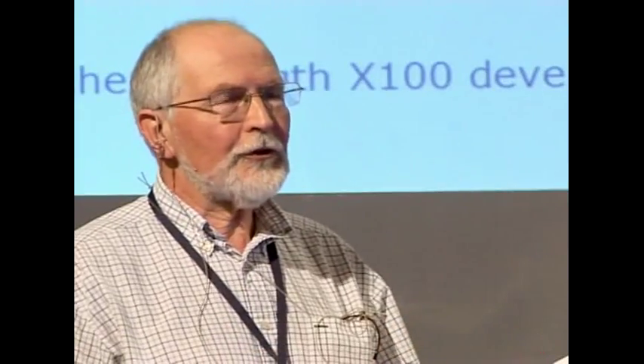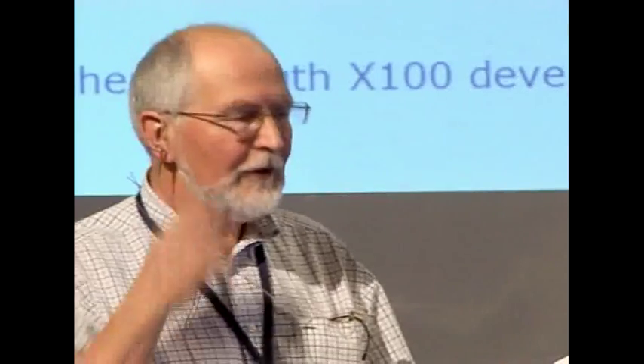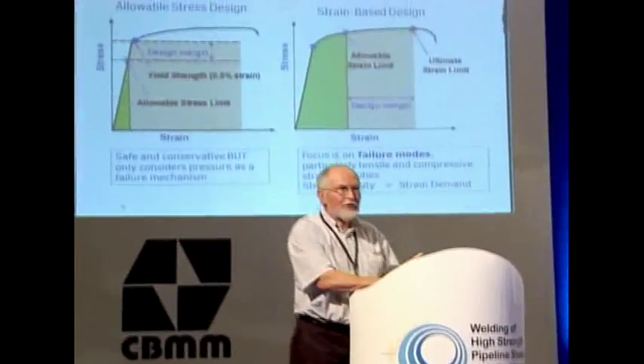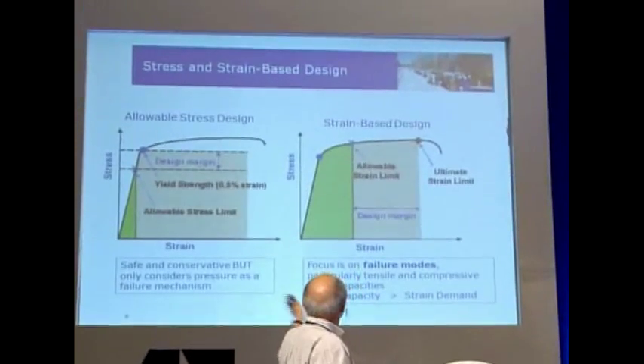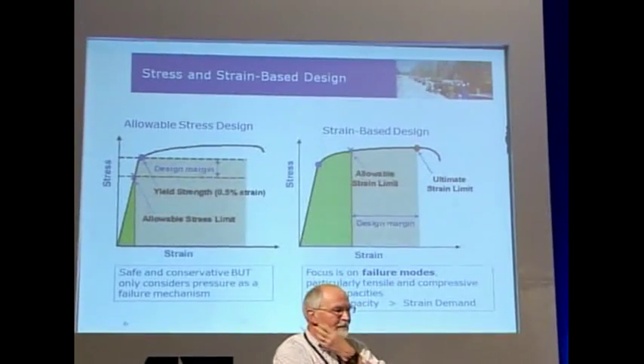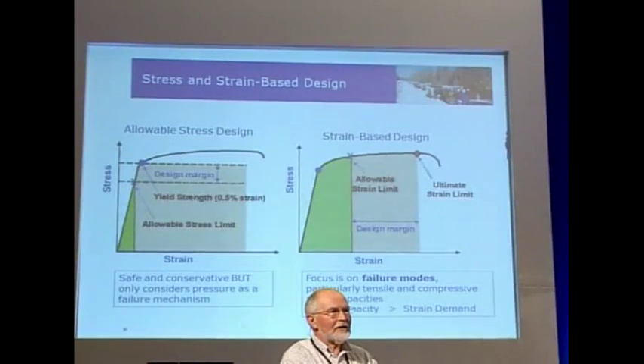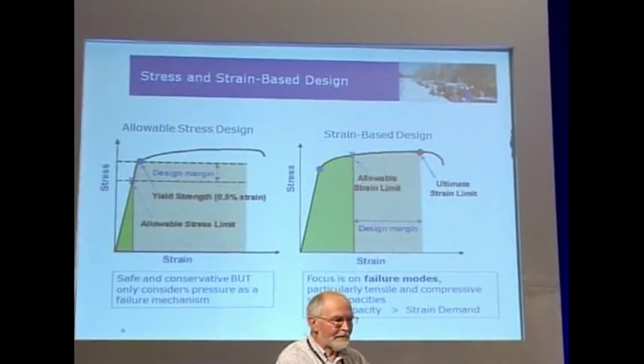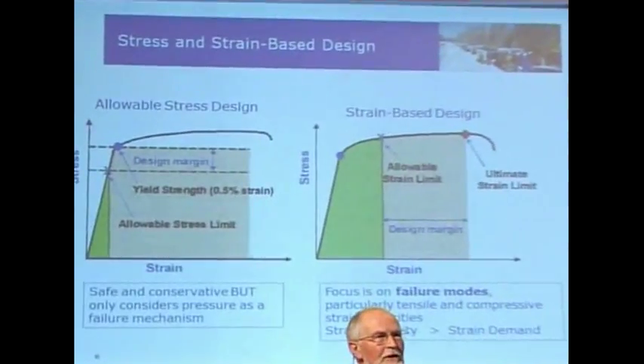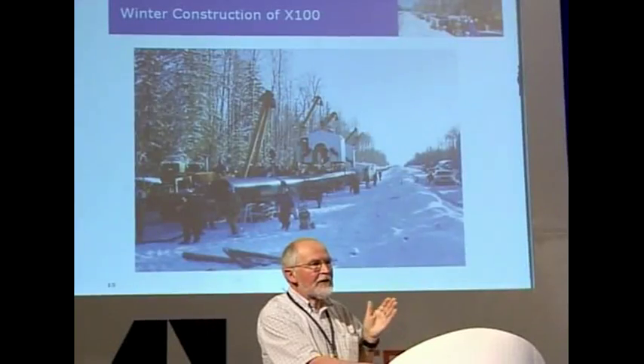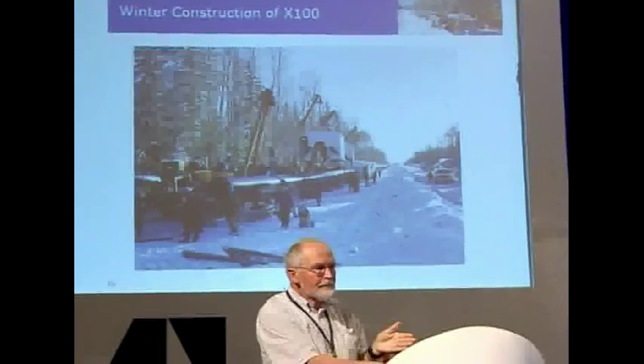Higher pipe strengths have the potential advantages of lower tonnages, lower material costs, reduced handling costs, improved field logistics, and reduced welding costs. However, Dr. Glover observed that account had to be taken of the significant reduction in usable ductility, which he estimated to be between 4 and 5% at X100 and between 1 and 2% at X120, which would almost certainly require a pipeline design relying on crack arresters. At present, X80 appears to be the optimum approach for most major projects.